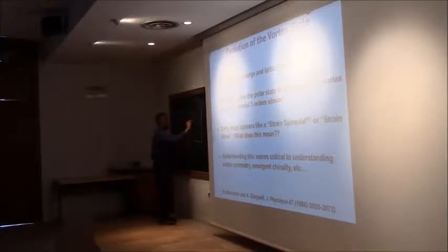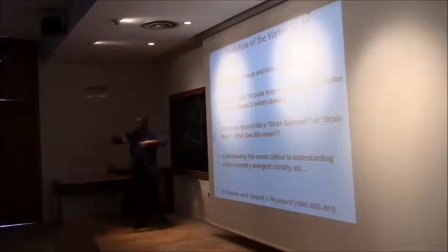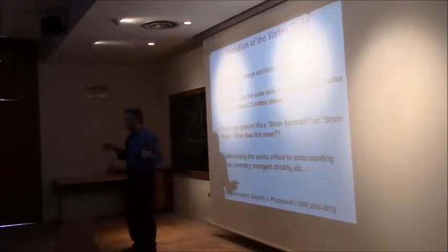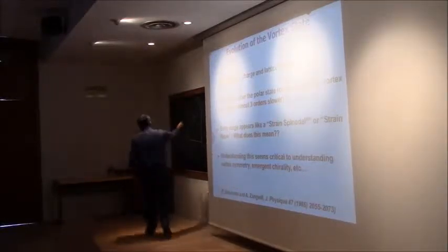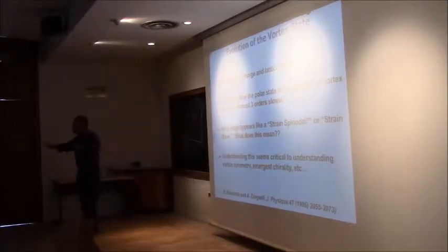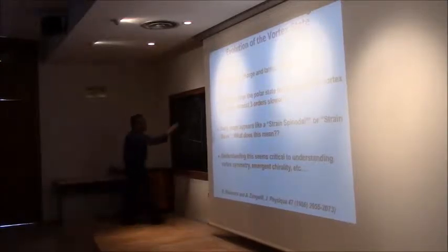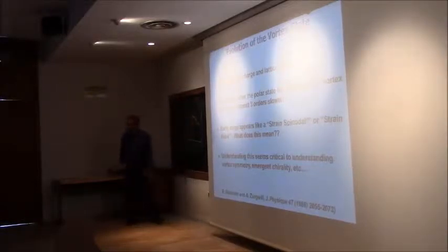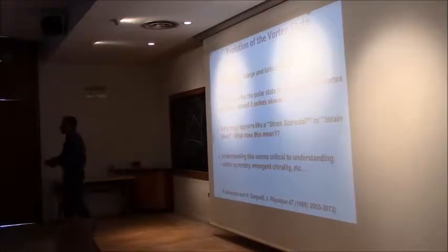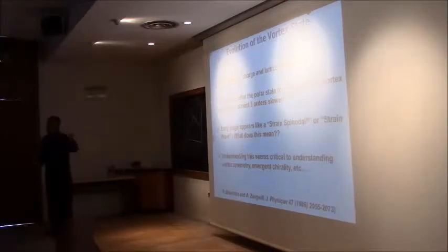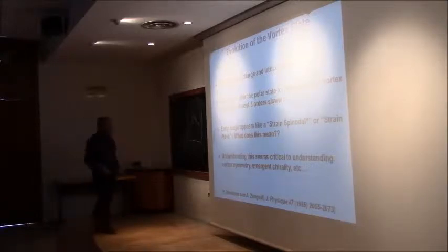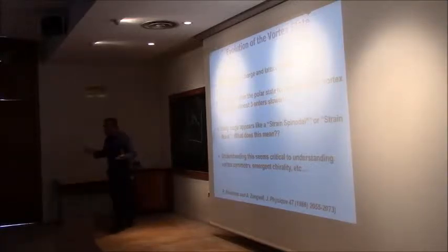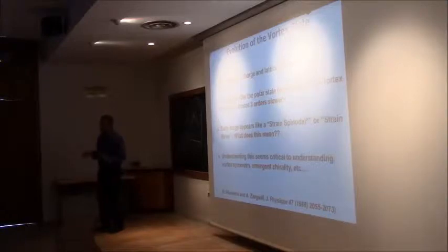And there are points within which the curvature, the second derivative, is negative. Which means, if I'm sitting here, the system spontaneously goes into two phases. It'll start rolling down the hill to here and here. There are no barriers. Unlike a classical process where, in any phase transformation, you have to nucleate and grow. There are no barriers. And it'll have multiple wavelengths, but we'll pick one wavelength at a time.